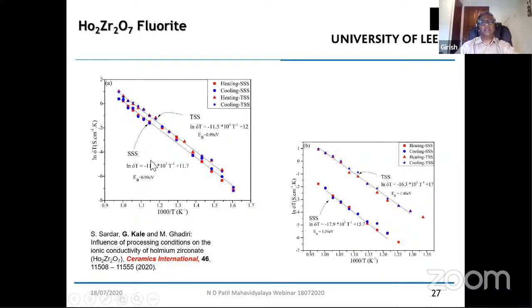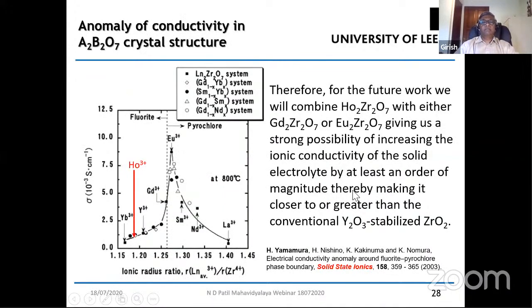So this is actually the comparison of ionic conductivity of the two-step sintering process compared to the single-step sintering process. Again, two-step is about half an order of magnitude higher than the single-step, the conventional sintering process. Okay, so the question is, how do we improve this ionic conductivity of A2B2O7, particularly the holmium zirconate that we have got?